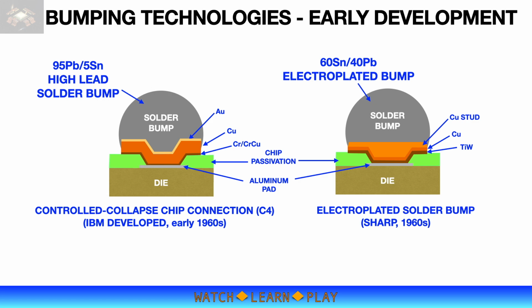IBM developed the flip chip process in the 1960s. IBM bumping technology was popularly called C4, which stands for Controlled Collapse Chip Connection. C4 technology utilizes high-lead solder bumps on pads of the chip and matching wettable terminals on ceramic substrate. During the reflow process, the solder bumps will self-align to the substrate terminals.